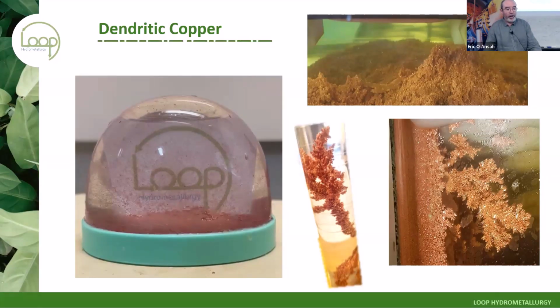For the longest time, the production of dendrite has been considered a major disadvantage of chloride chemistry. One other technology prior to us was called the Intec process. Intec was an Australian company that spent approximately $70 million developing technology in this field. They did develop an electrowinning cell that unfortunately had a number of potential points of failure. So if you could afford to have a person stand there and watch it 24 hours a day, 7 days a week and fix every problem as it occurred, you could have built it. But of course, that's not commercially viable. So it never got to market.